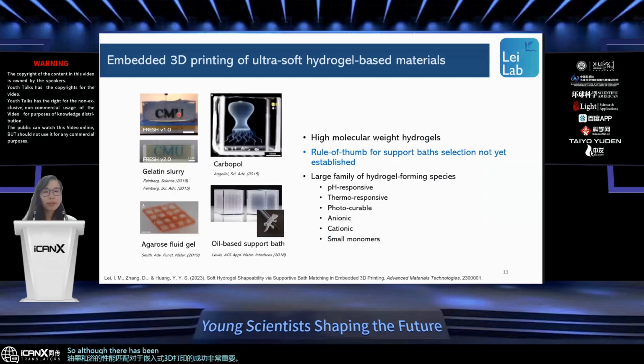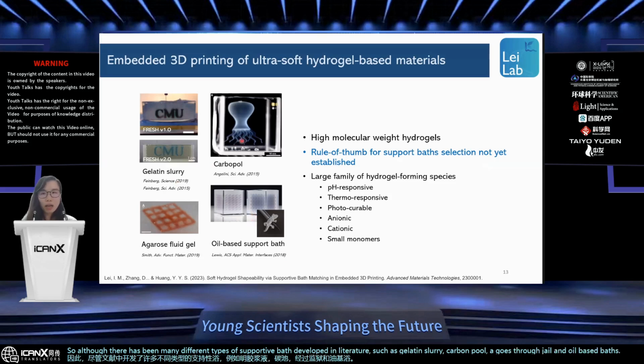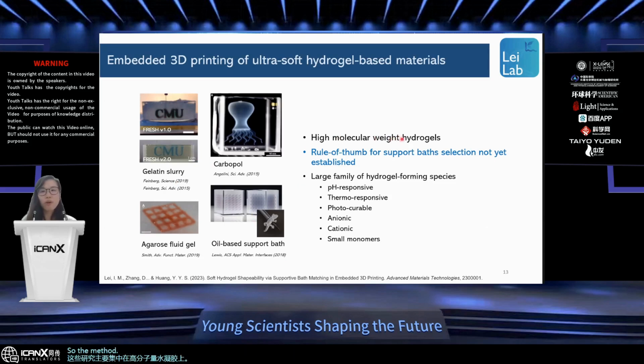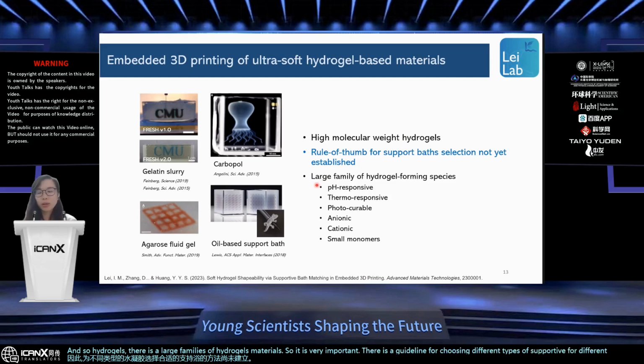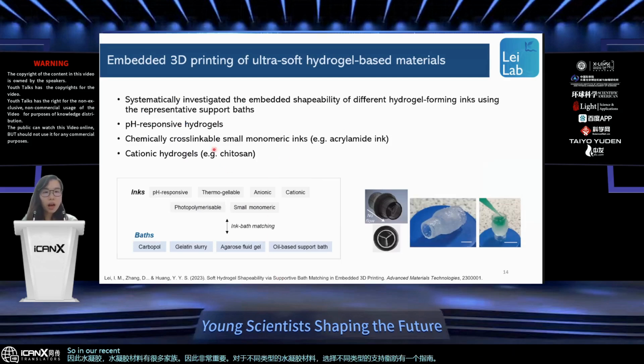Although many different types of supportive bath have been developed in literature, such as gelatin slurry, Carbopol, agarose fluid gel, and oil-based supportive bath, these studies mostly focus on high molecular weight hydrogels. So the methodology for choosing the suitable supportive bath for different types of hydrogels has not yet been established. There is a large family of hydrogel materials, so it is very important to have a guideline for choosing different types of supportive bath for different types of hydrogel materials. So in our recent work, we have systematically investigated the embedded shapeability of different hydrogel materials using the